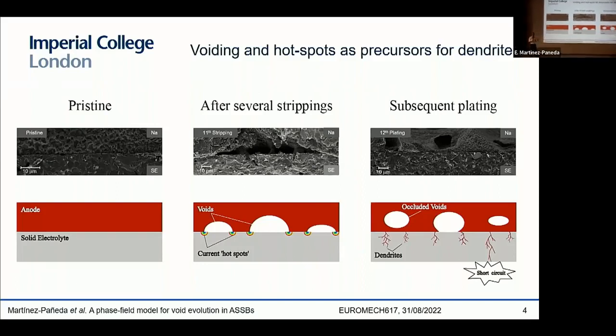Essentially, we need to minimize voiding and we need to minimize current hotspots if we want to minimize dendrite nucleation and growth. One of the key hypotheses in the community is that the most effective way of minimizing those voids and those current hotspots is by applying a constant mechanical pressure on top of the anode, so a stack pressure.